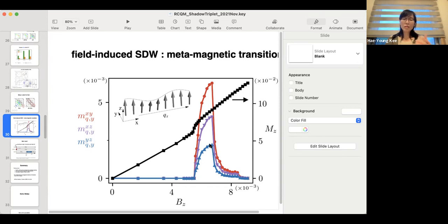We did a VASP, the LDA calculation to get the tight binding parameters, and you can have small changes, so we'll still end up with inter-orbital superconductors. Of course, pairing symmetry will be very sensitive to what type of spin-orbit coupling we have, because you can have a lambda naught, or you can have D-wave spin-orbit coupling, and so on.